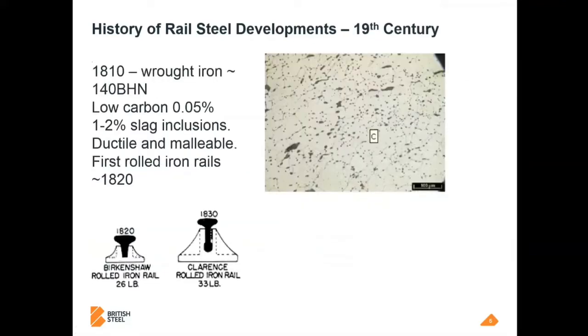But because rail is an intrinsically long product, and the longer the better, it was obvious from the beginning that you needed to produce a rolled profile. And for that, at the time, the available technology was low carbon wrought iron. It would allow you to put them through a simple rolling mill, get a length maybe 15 foot, 20 foot, maybe even up to 30 foot in the later years. And that's a sort of length of rail that starts to become more credible and more attractive. And the costs start to come down as the railways start to propagate through the country and become more popular. Obviously, cost is an important driver.